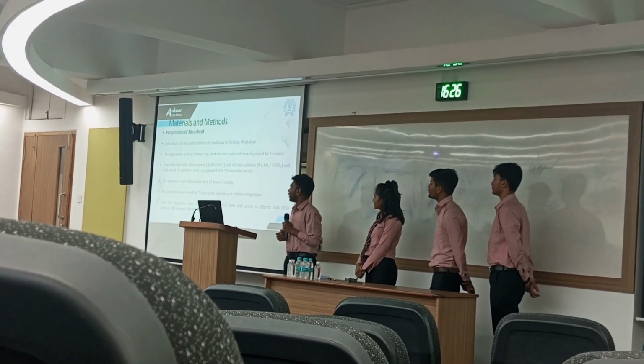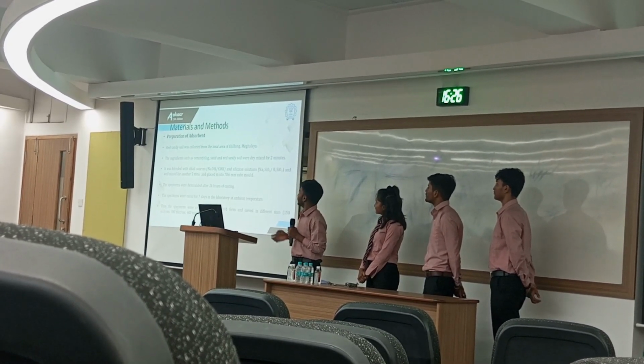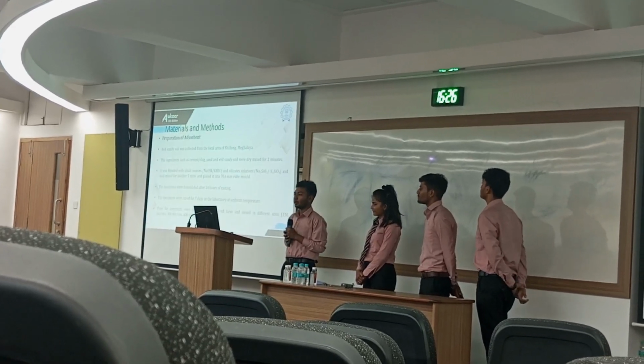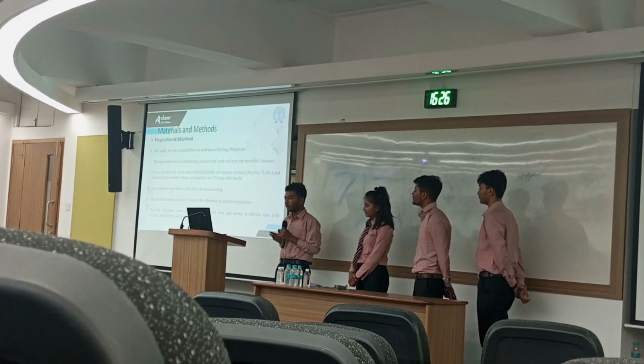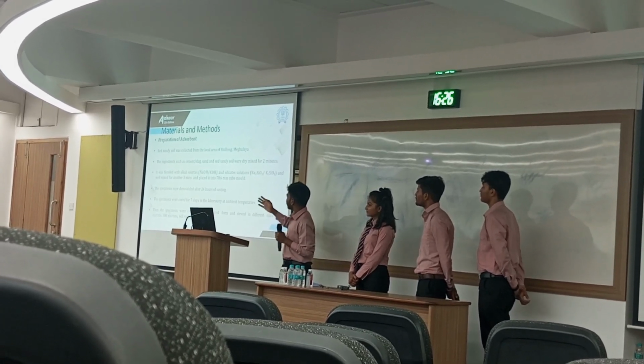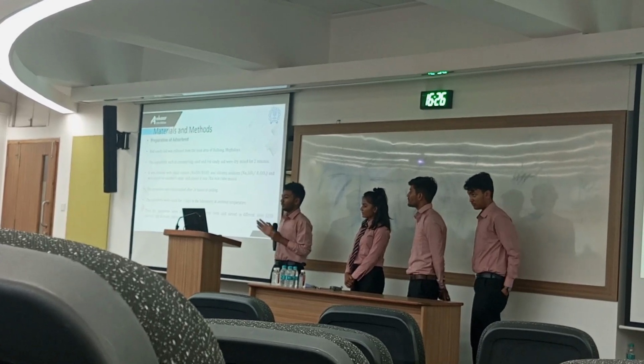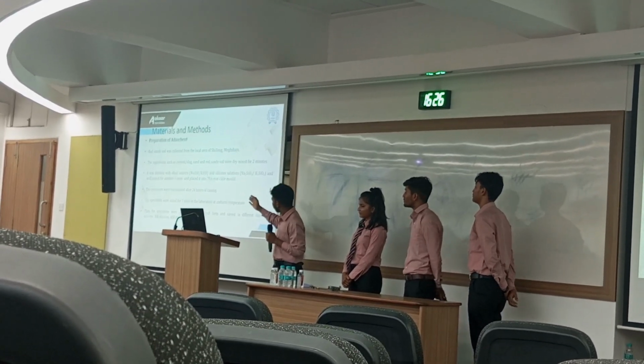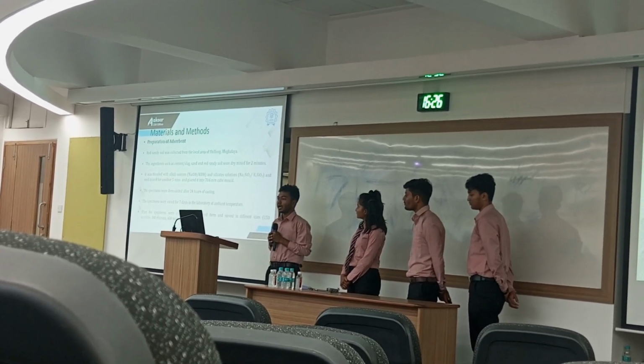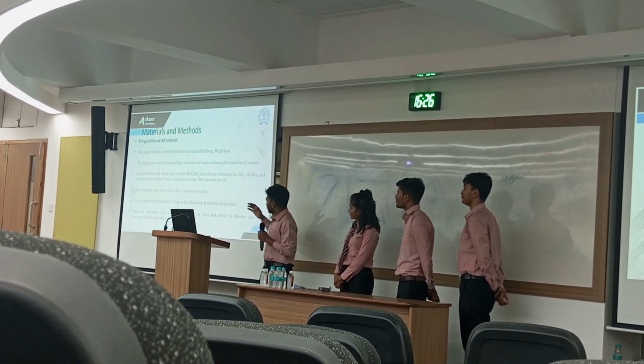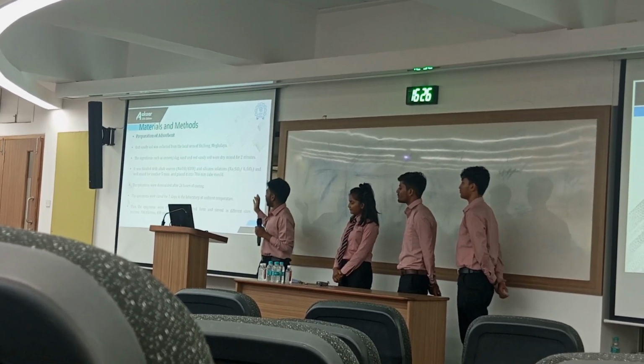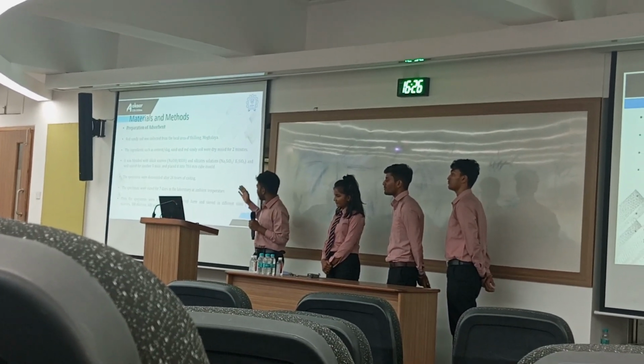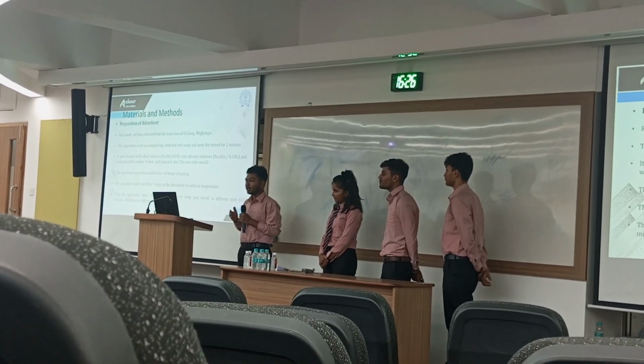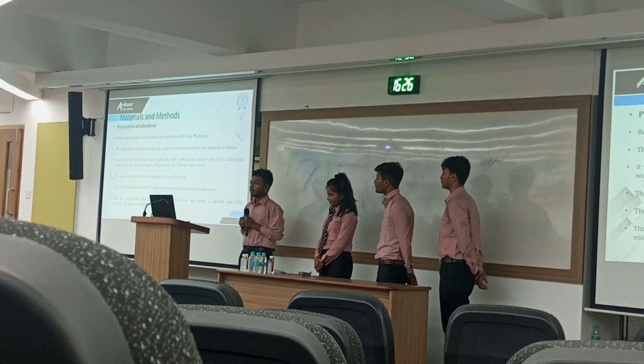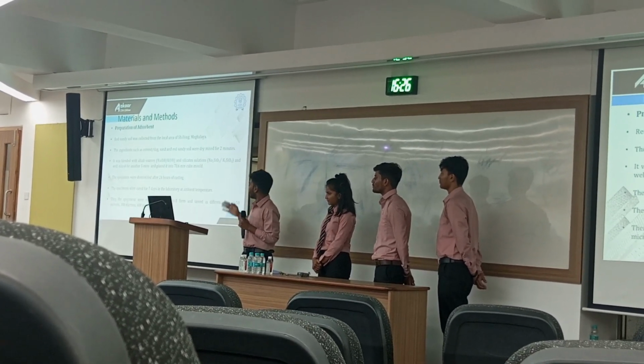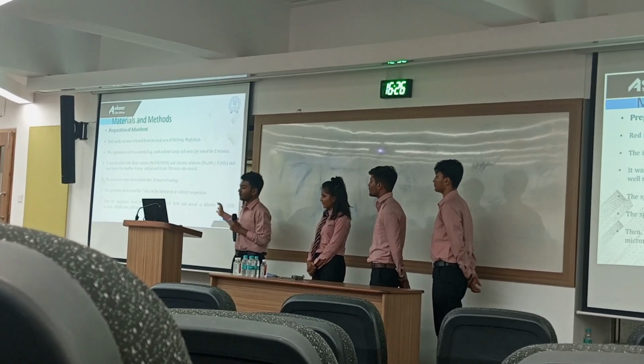Thank you so much. Now I would like to dive deeper and discuss the materials and method of removal of methylene blue from the aqueous solution. In the adsorption process, we need an adsorbent and an adsorbate. For making the adsorbent, at first we mix the red sandy soil and cement for 2 minutes. After mixing it well, we add sodium hydroxide and sodium silicate and mix it for another 5 minutes. Then we place it in a 70.6 mm cube mold and rest it for 24 hours. After 24 hours of casting, we demold the specimen and cure it for 7 days at ambient temperature. Then we crush the specimen into powder form and sieve it with different sieve sizes: 150 micron, 300 micron and 600 micron.